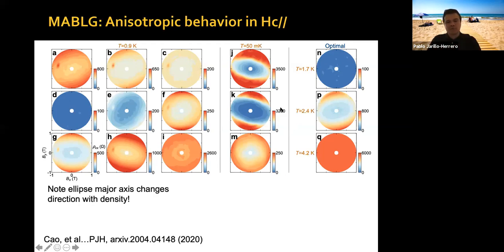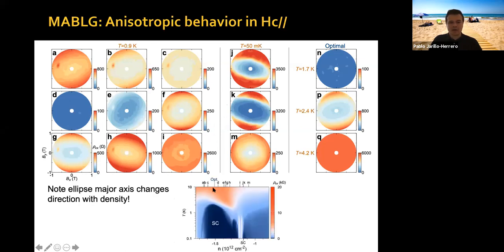This is quite complicated. You can look for details in this paper, but the thing that I want you to take away is that the ellipse at this doping, in panel E, has a different orientation than the ellipse in panel H, which is similar to this one here. In fact, each of these panels is taken along one of these at different dopings. And what you can see is that the ellipse major axis changes direction, rotates with density.